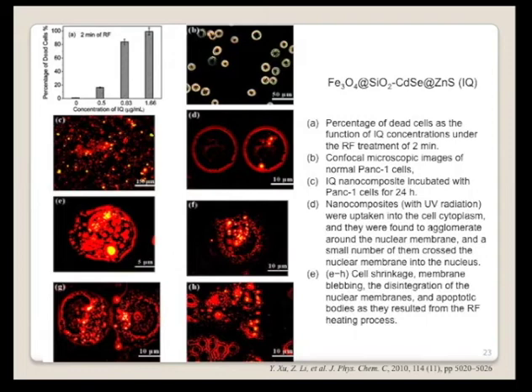Image D is what we got from the nanoparticles under UV excitation. They are taken into the cell cytoplasm of the pancreatic cells. You can see some particles at the membrane of the cell, and also going inside, even going to the nucleus. So it means this particle is still small enough that it can diffuse into the cell and even into the nucleus through different channels. Okay.